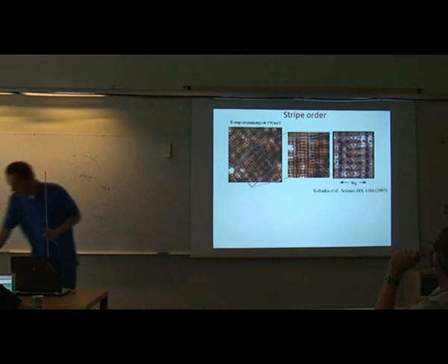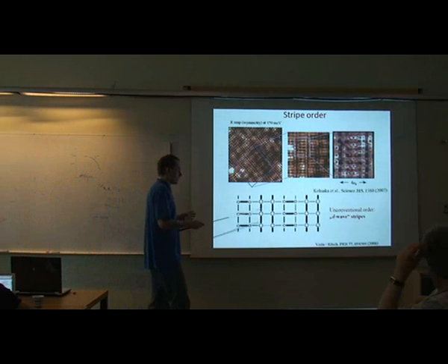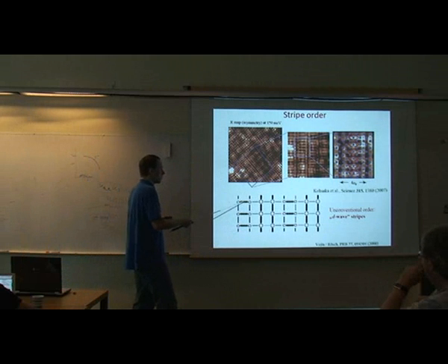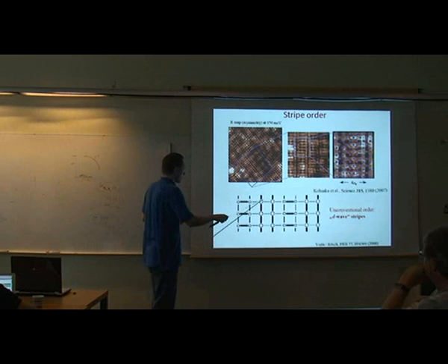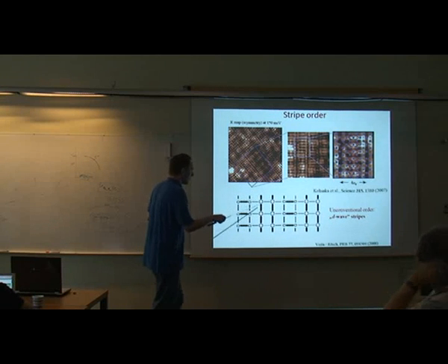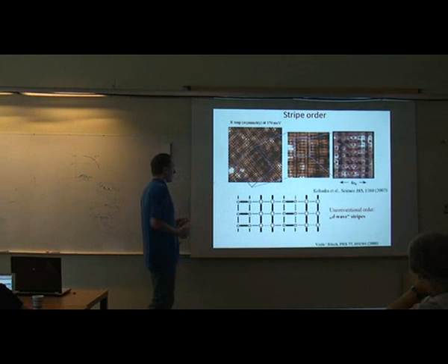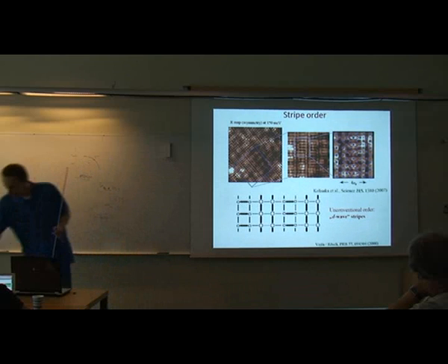And what's specific about this pattern, why I show it to you, it also has a peculiar feature, at least this has been proposed theoretically, that bond amplitudes between these atoms are modulated as well. It's not only the charge, which are these circles, also these bonds, and in this case they have a D-wave pattern, so X and Y direction are inequivalent, and this has been proposed to explain this particular pattern. That's one of the patterns I will be considering.